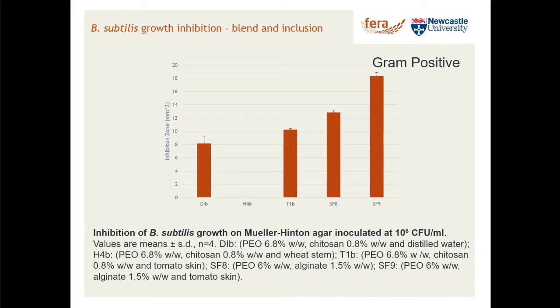Again, our Bacillus subtilis, and different types and different blends of materials. So we've got things like alginate, chitosan, PEO, and in different proportions as well. And this is something we're starting to look at with and without tomato skin processed material as well. And again, we see quite a wide range of effects, but certainly in one case, we got a fairly good enhancement of our inhibition. And this particular one was a combination of PEO, alginate, and tomato skin. And this is something we're starting to explore further. Which sorts of materials and what combinations give us the best effects?